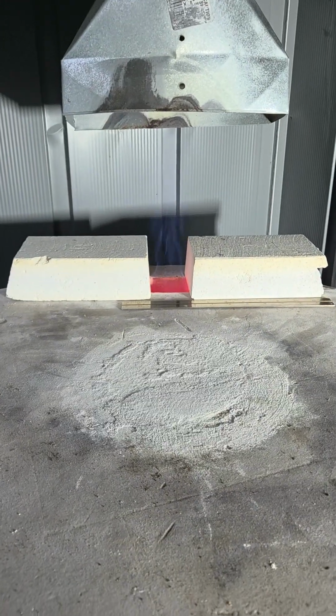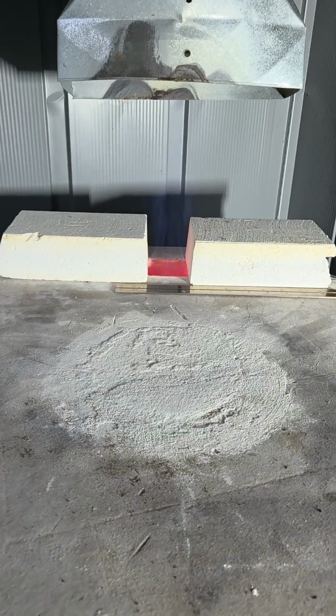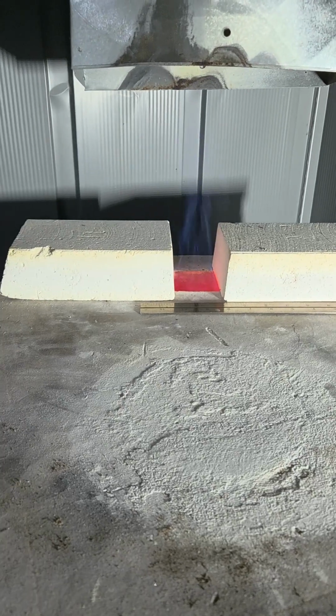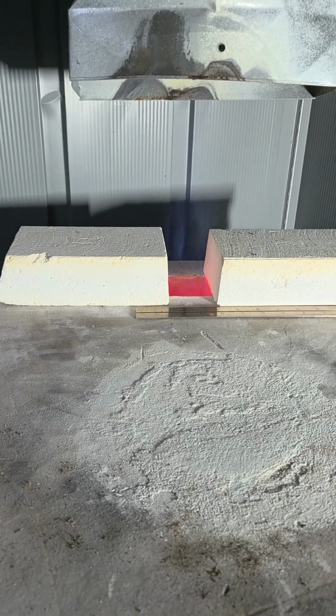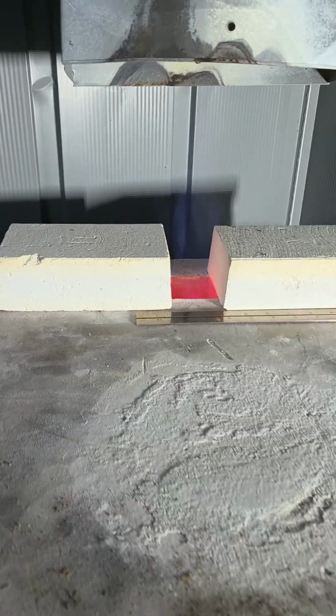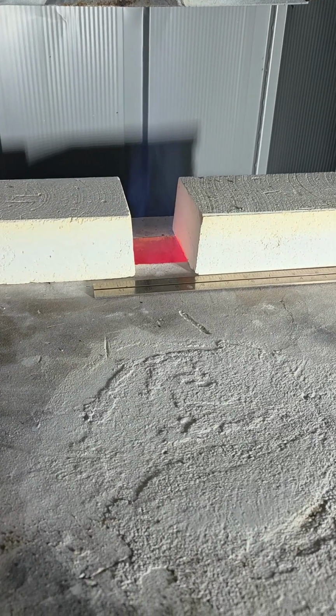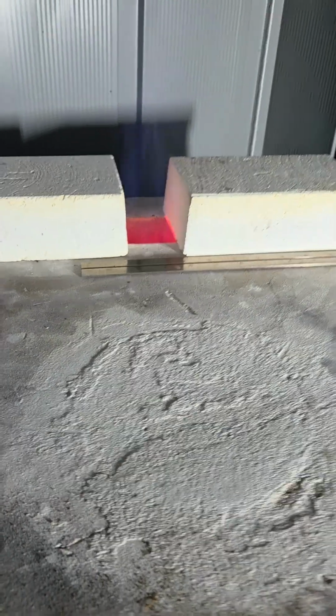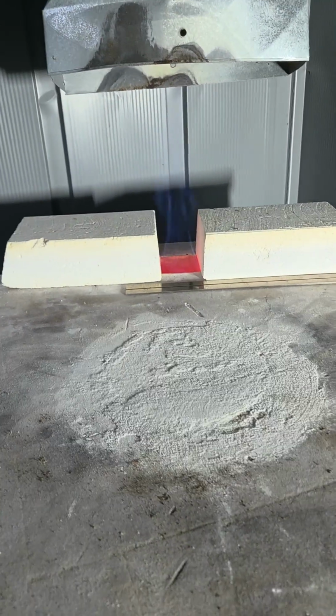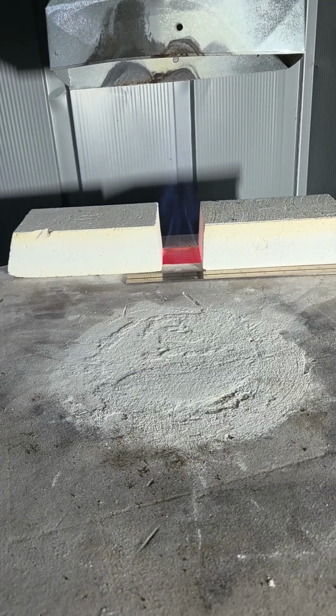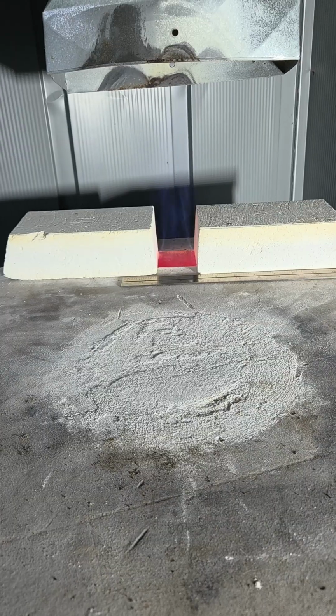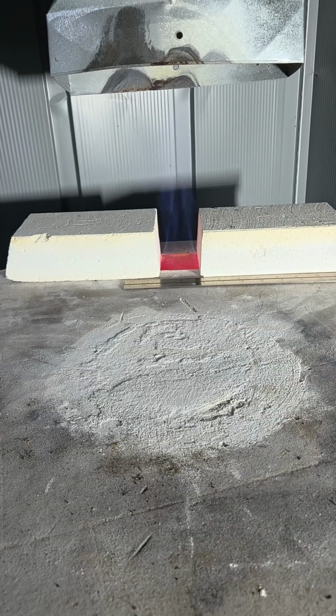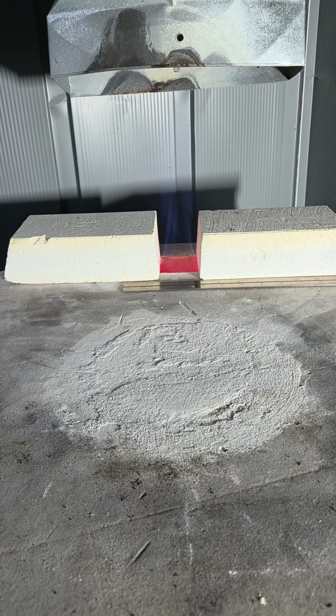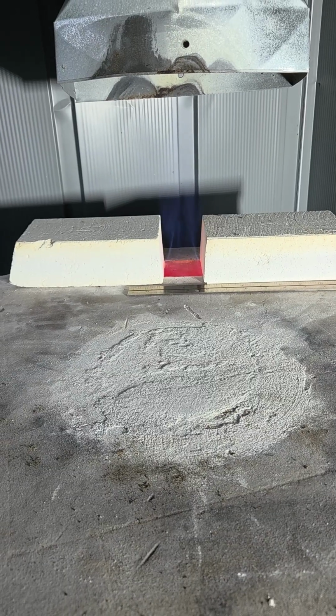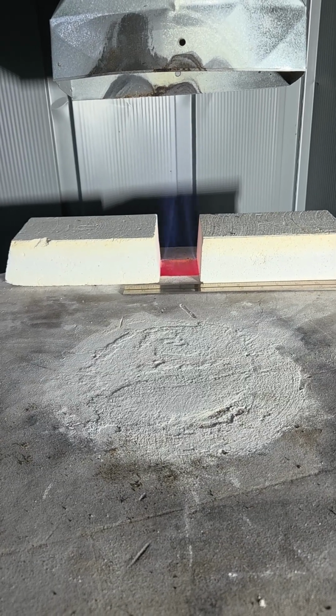So it has crept up to about 930 degrees, and so now I'm just going to go ahead and move the block in maybe 1/8 of an inch, 1/16 of an inch. So that was probably 1/8 of an inch, and I'll just wait a few minutes, see where the temperature stabilizes, and I'm going to try and keep it at around 930. It's got about 10 to 15 minutes remaining for a body reduction.